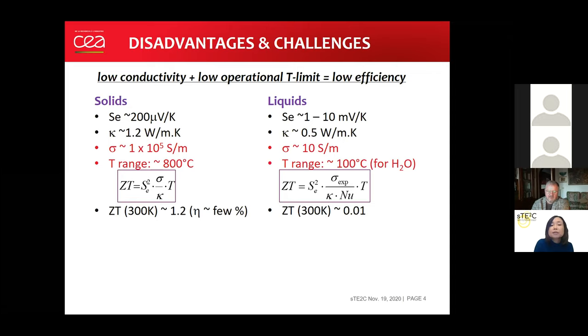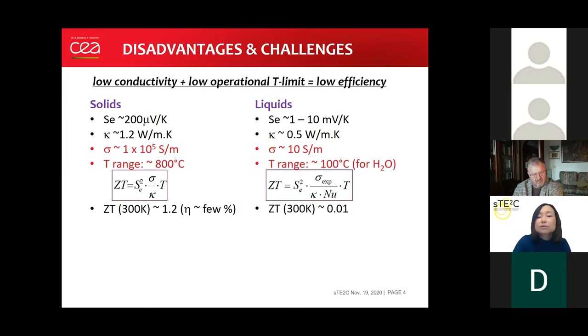Despite the fact that the dimensionless figure of merit becomes very small compared to the room temperature ZT, the record is around one order of magnitude smaller than the solid state counterpart.